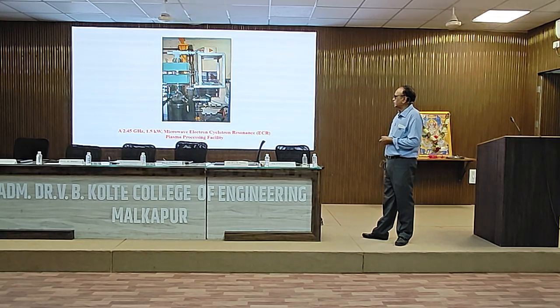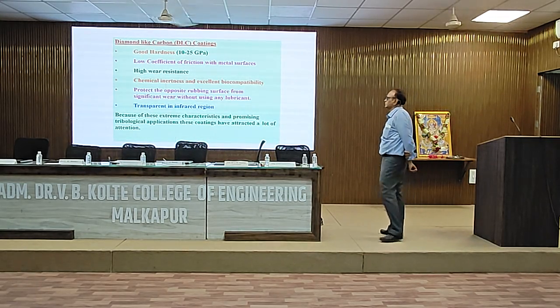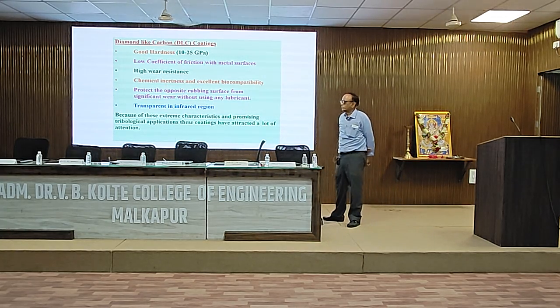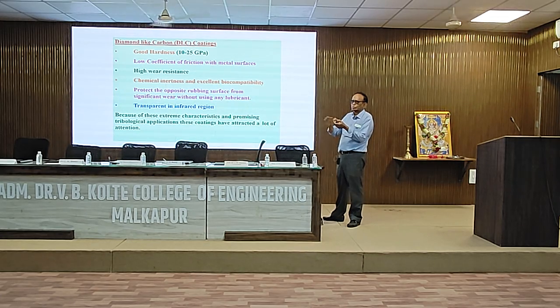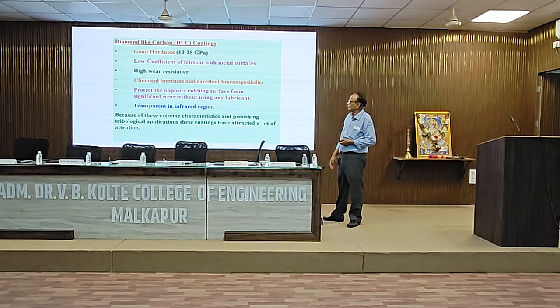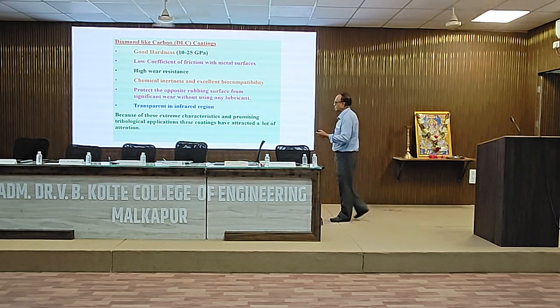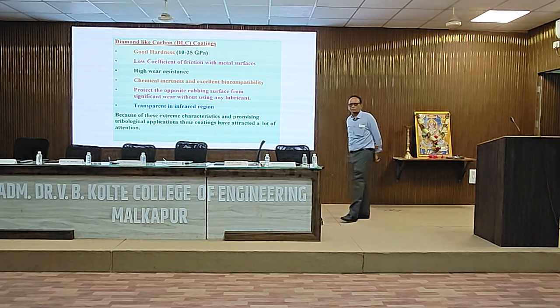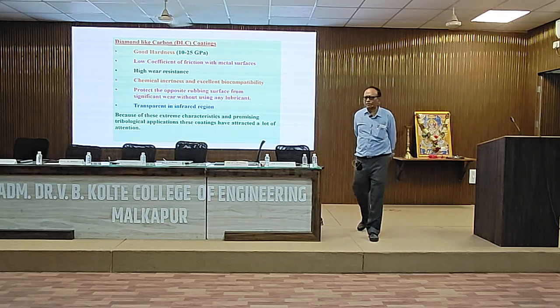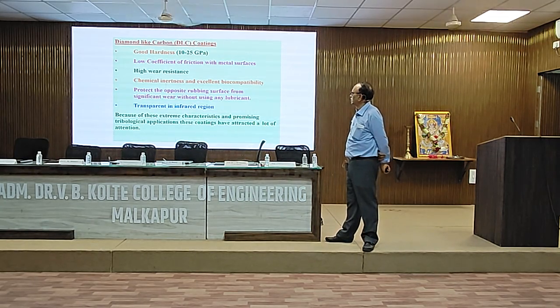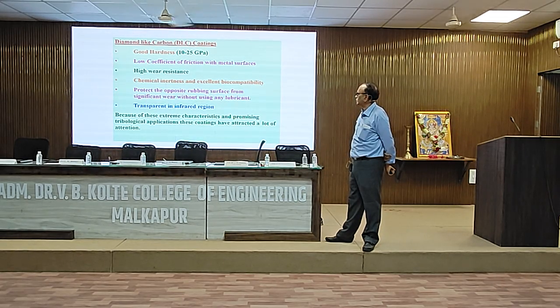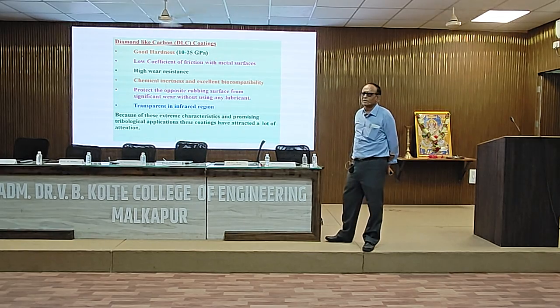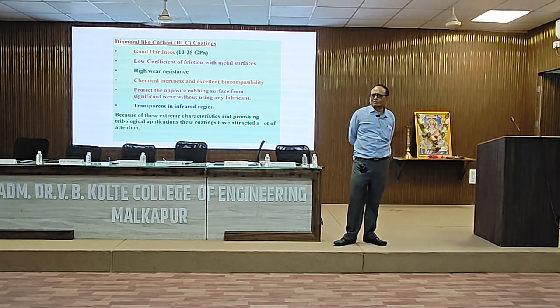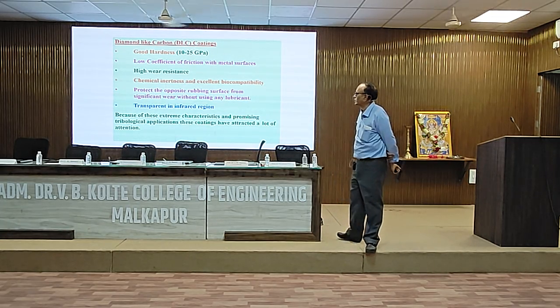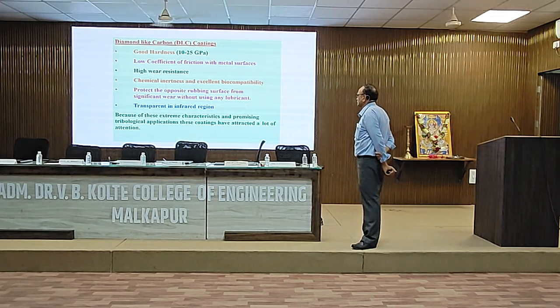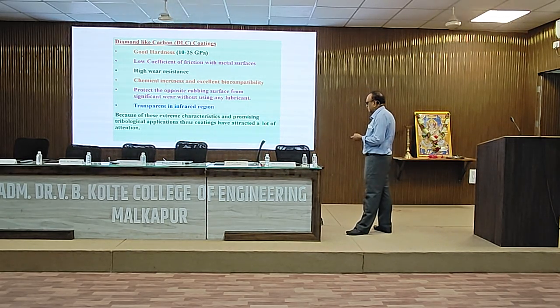See, this is how the facility looks. And diamond-like carbon, the one which I just explained to you, has very good hardness, 10 to 25 gigapascal, low coefficient of friction because it's a smooth coating. So it gives very low coefficient of friction with the metal surface, high wear resistance, chemical inertness because it's a carbon coating, excellent biocompatibility. Most of the heart valves that were implanted into patients were made of pyrolytic graphite, and on that the coating of diamond-like carbon is given. They are biocompatible. It protects the opposite rubbing surfaces from significant wear without using any lubricant, and it's transparent to infrared radiation, because for your military applications, for your germanium optics, night vision devices, these coatings are very, very important. And because of these extreme characteristics, they have attracted a lot of attention.